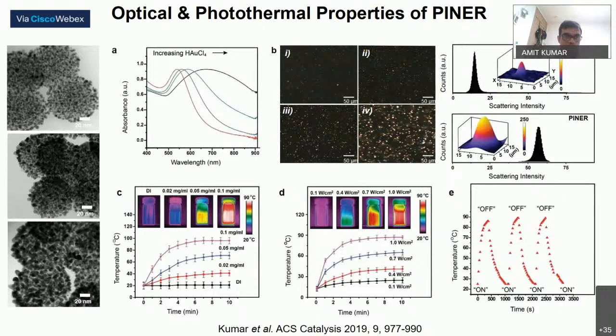As you can see, these are optical absorption spectra of nanoreactors having different sizes of plasmonic component. In the largest size, you can see the absorption is very broad and it extends into the NIR region. Such NIR absorption is very crucial for biomedical applications, because tissues and cells absorb minimally in the NIR region. And one more important feature we got is their dark field light scattering.